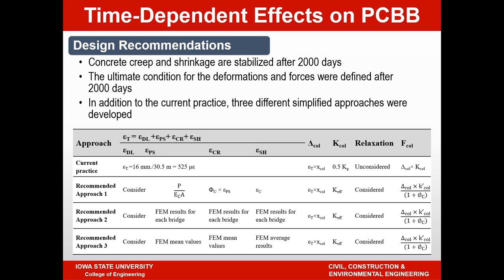So you would expect this approach to be more accurate because each and every bridge was modeled based on what we learned from the analysis of finite element. The third approach is probably the most realistic in terms of making a recommendation, in that we took the average of the finite element results. So in other words, we have results for the eight different bridges. We took the averages and we established them as the recommended values.